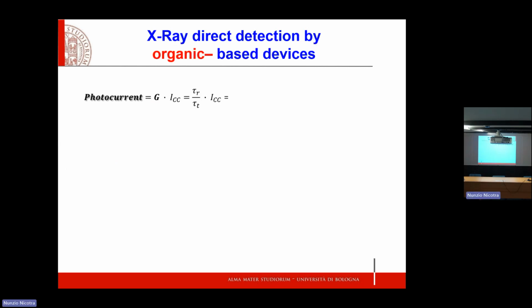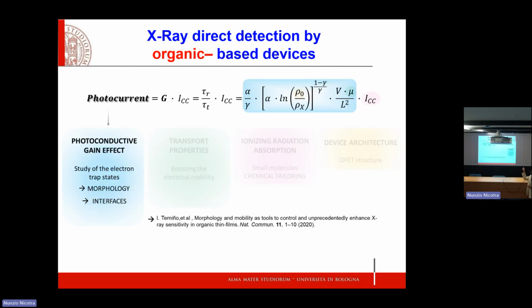Now that we know what is the cause for this collected current, and we know that defects have a very strong role in capturing and holding on to one of the carriers, how can we exploit this knowledge to control the behavior of the material? This is the expression of the photocurrent gain, G. If we introduce the expressions of tau R and tau T, we can see here in full bloom, and we clearly see what the parameters are that we can play with to enhance G and thus the collected photocurrent.